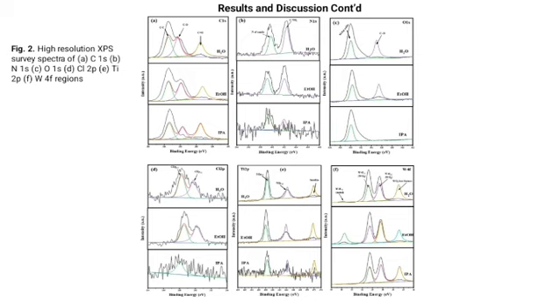tungsten metal. However, in all the materials, the tungsten peaks were observed at 35 electron volts, 37 electron volts, and 41 electron volts, all corresponding to the W4F 7/2, W4F 5/2, and tungsten oxide loss features, which are also accounting for the different oxidation states in tungsten oxide.